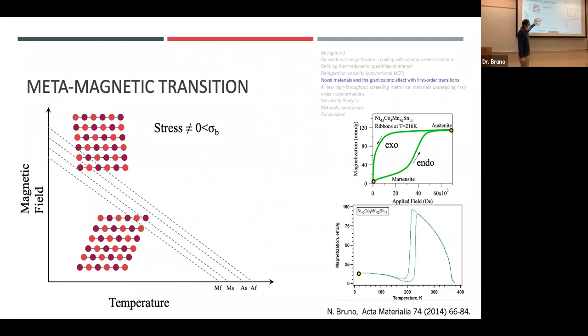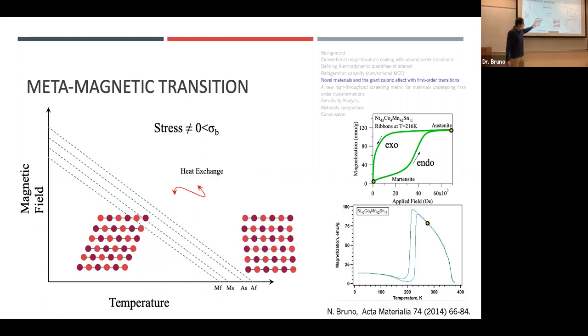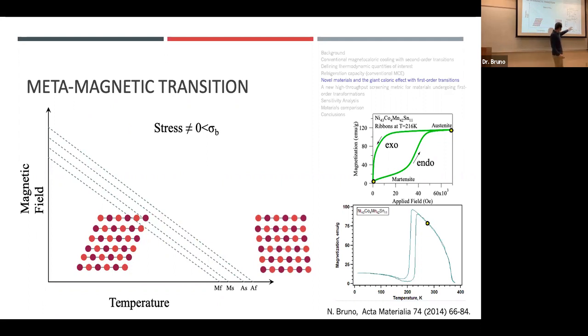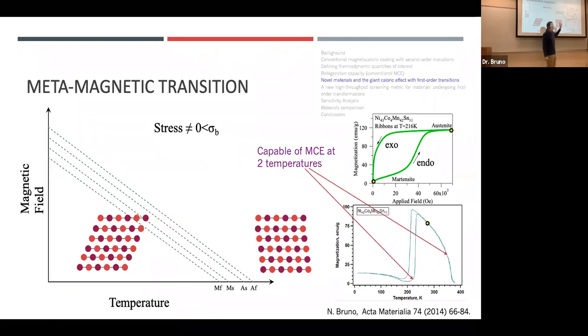We can also heat martensite up, which is, like I said, magnetization versus temperature. Martensite's non-magnetic. We heat it up, maybe we'll have some magnetic transition here, like at the Néel temperature or something, some antiferromagnetic material. We'll transform it into the austenite phase, get the latent heat. If we were to continue heating austenite, we're going to reach its ferromagnetic Curie point. So actually, this material is capable of the magnetocaloric effect at two distinct temperatures, one at the Curie point and one at the transformation through latent heat.